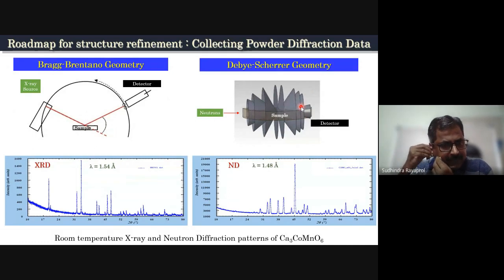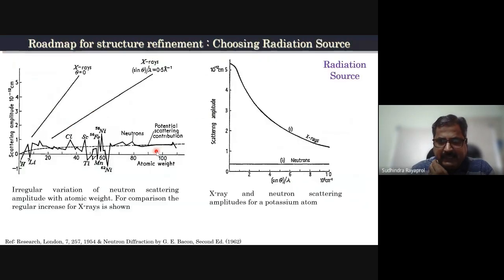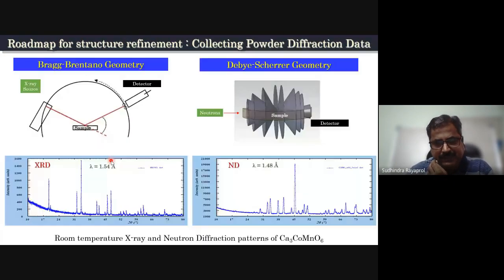So this is one typical example for one compound, which we'll encounter later also. This is the same sample at almost identical wavelengths: 1.54 angstroms for X-rays, and for neutron diffraction it is 1.48 angstroms. The same composition shows different patterns, and the reason for that, as I said, is the scattering of X-rays as a function of atomic number, which is different for X-rays and neutrons.